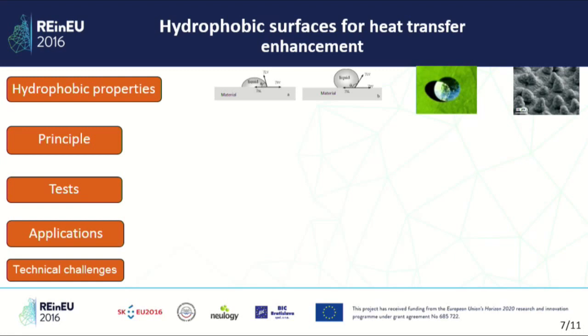Hydrophobic surfaces could be used for heat transfer enhancement. We have known for a long time that when a drop is put on a surface, it can spread. In that case, it is hydrophilic. But if it doesn't spread, it is hydrophobic. And the degree of hydrophobicity can be characterized by what we call the contact angle. That is the angle between the surface and the tangent to the drop.